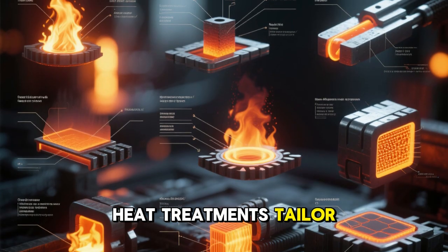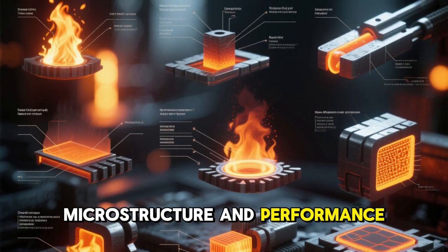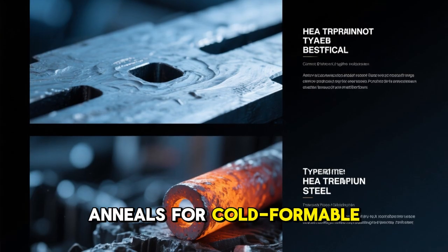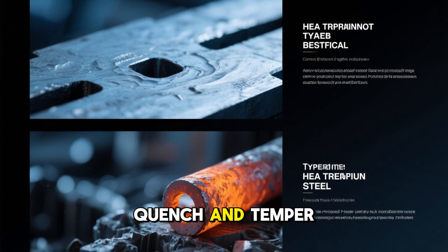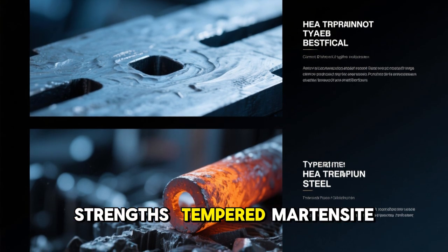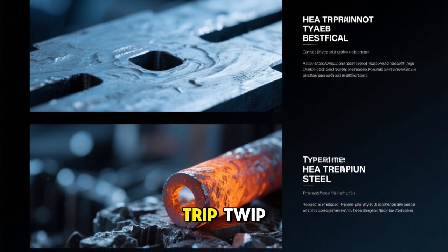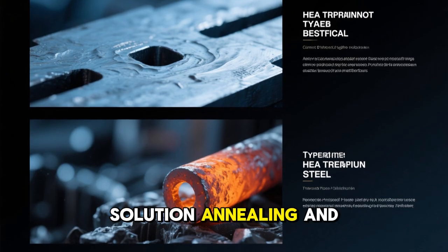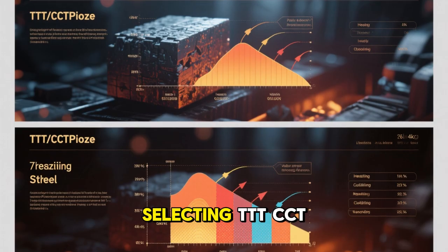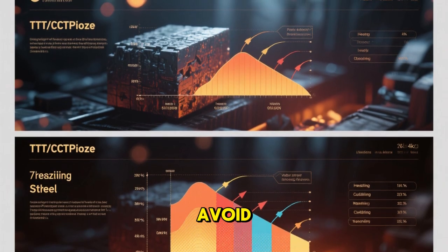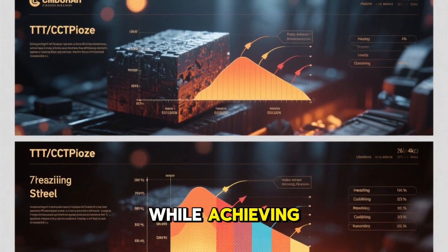Heat treatments tailor microstructure and performance. Spheroidizing anneals for cold formable grades, normalizing to refine grain, quench and temper for high strengths, tempered martensite, controlled bainite transformations, TRIP, TWIP strategies for automotive steels, solution annealing and passivation for stainless. Selecting TTT, CCT paths and heating-cooling parameters is critical to avoid distortion and cracking while achieving toughness, hardness, and formability.